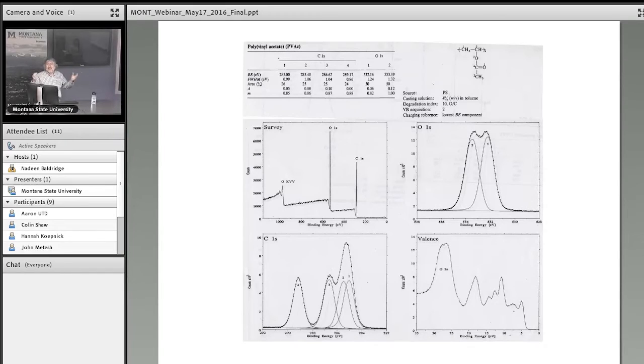This is the overall spectra. This is the oxygen, this is the carbon peak, this is the oxygen Auger, like the Auger we were discussing, and they're all going to show up in your spectra. So you have to know what they are. And then when you zoom into them, with oxygen you get this, with carbon you get this. So that's the kind of information you can get: the oxidation state of your material of interest.